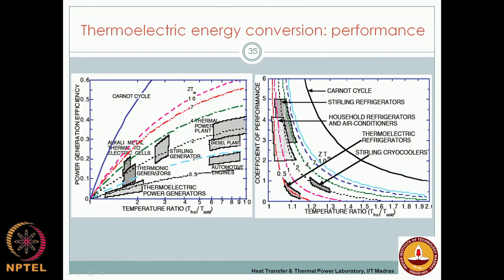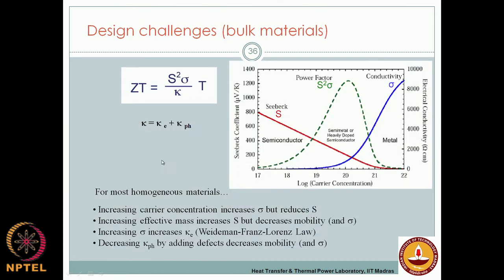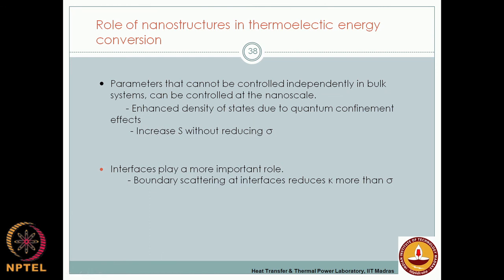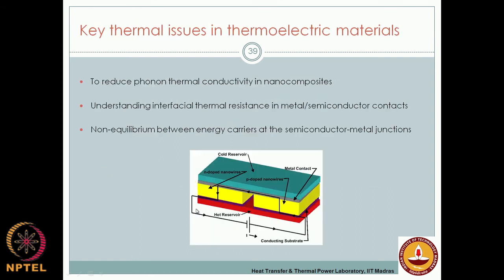Now, if you see that if you have a thermoelectric figure of merit of 4 and you are operating in the lower temperature range, because the temperature ratios with thermoelectric generation are usually in the lower end, you cannot use it like you use your internal combustion engines, you do not operate at very high temperature ratios. So, at this range with the thermoelectric figure of merit of 4, you can push it to close to 30%, and if your thermoelectric figure of merit climbs to 7 or 10, you are pushing this further, right. So, this is where the role of nanoscale materials comes into the picture. You can use these nanoscale thin film technologies as potential thermoelectric materials.